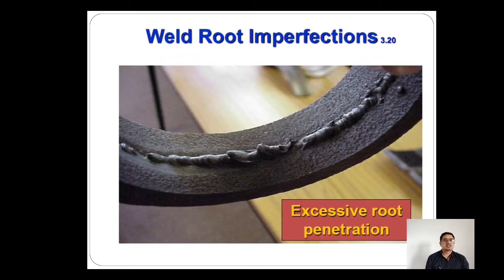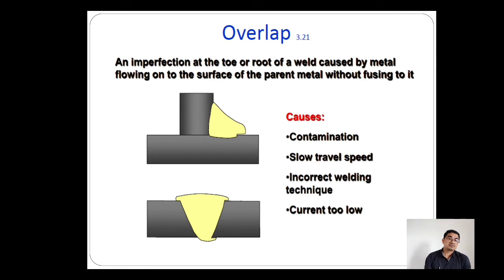So friends, in this picture you can see the weld reinforcement in the root of the weld. That is the bevel and this is the root. On the root side you can see the high reinforcement, that is called excessive root penetration. It may happen because the welder is performing welding and stops in a particular location with higher current. You can also say low travel speed.